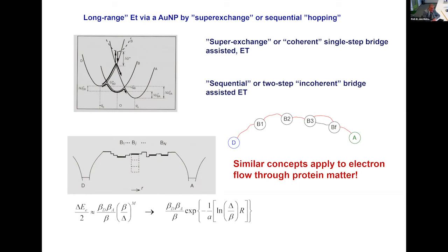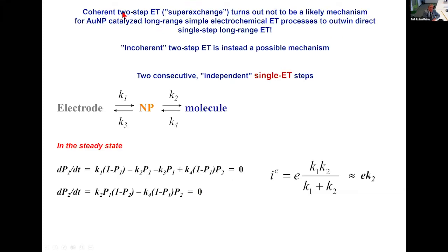So these are the two mechanisms. Our investigations show the superexchange or the tunneling. Tunneling is also called superexchange, and I am prepared to stand up and defend that this is the same as tunneling. That turns out not to be a likely mechanism for various reasons that I can explain given the time. But the two-step electron transfer is a possible mechanism. That would be sequential electron transfer from the electrode to the nanoparticle and further on to the molecule, or the opposite way. And in the steady state, this corresponds to normal consecutive reactions, giving a current form like this one, with the two forward rate constants, and we disregard the reverse rate constants. And if one of them is much bigger than the other one, then it reduces to a single rate constant.